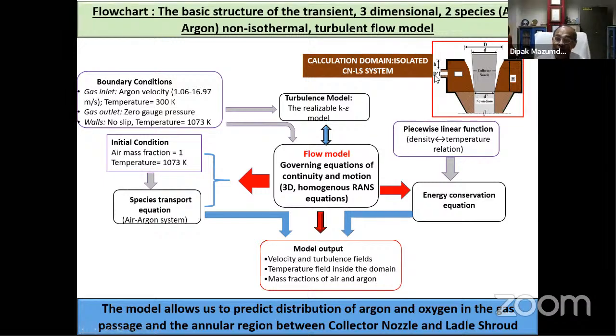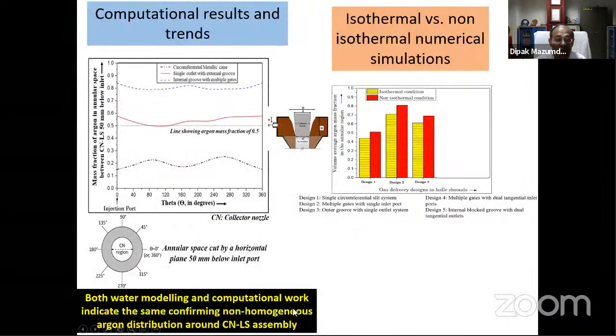Then we have a turbulent flow because the Reynolds number is high, and we have a 3-dimensional Navier-Stokes equation, and then we have calculated the flow distribution here and tried to find out what is the profile of argon, how much argon, what is the distribution pattern of argon around this collector nozzle. And if we compare the 3 different cases, this shows us the worst case, where it shows the distribution of argon. And what is this distribution?